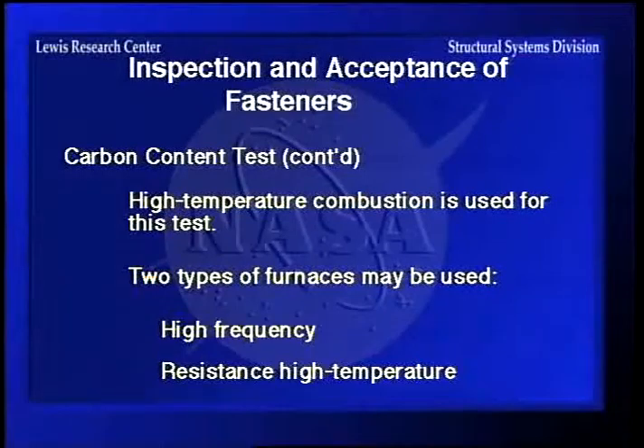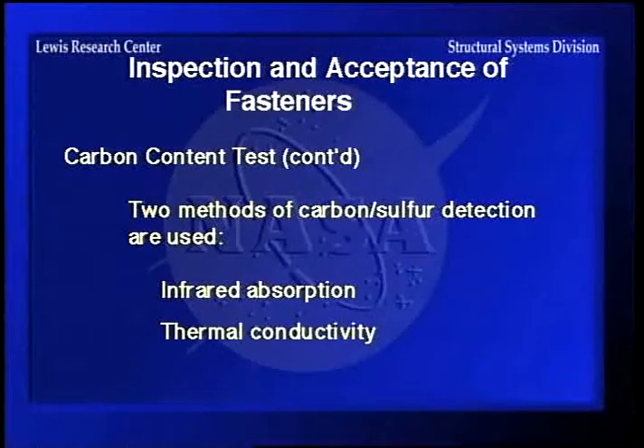So one of the tests that is used on acceptance of alloy steel fasteners is a carbon content test. And there's different ways of doing it. One of the companies that I believe makes the equipment that we have around here is called LECO. And what you have is some type of a furnace, either an induction or high frequency type or resistance type furnace, and you take a little chunk of this stuff and put enough oxygen in with it that you can burn it. And then you have different ways of measuring by getting the carbon dioxide from the combustion. You can measure it and get the carbon content out of your sample.